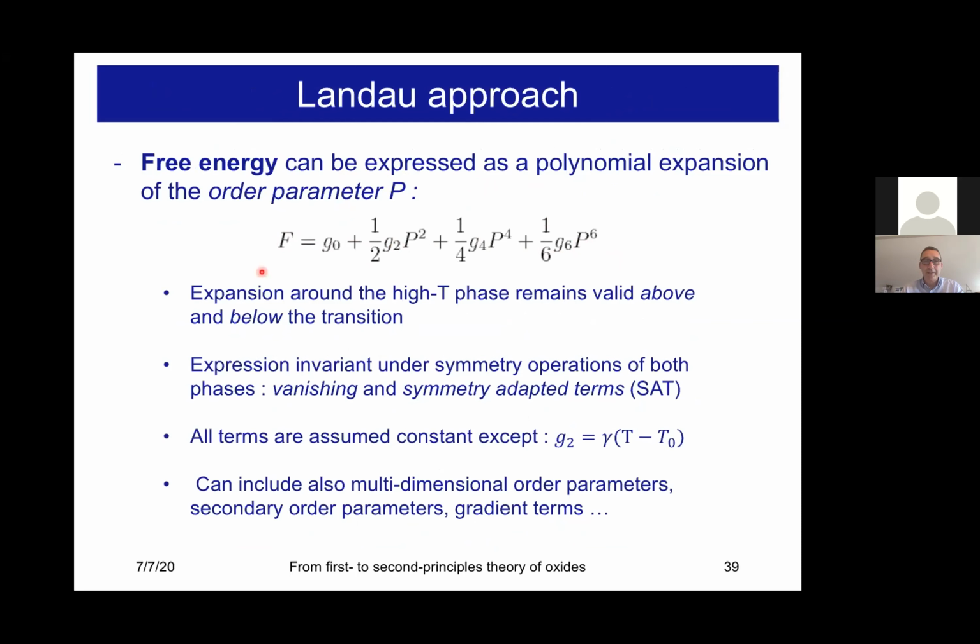And what is interesting is that the expansion around the high temperature phase should remain valid above and below the transition. So it means that this expansion is the same when you are above and below. And also it means that the expression that we get for the free energy, of course, if it applies to the high symmetry and the low symmetry phase, it should respect the symmetry operations of both phases. So it means that basically when you...